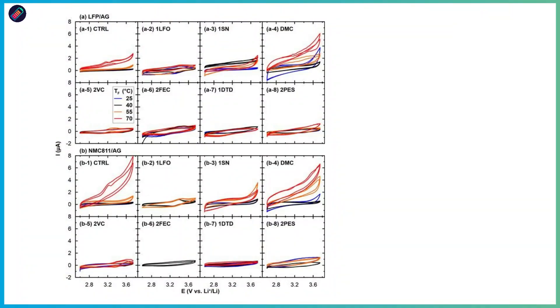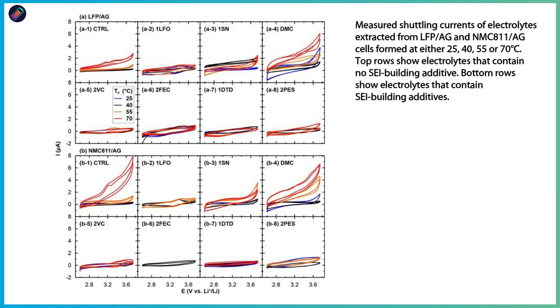Now we wanted to know — we had identified that our reversible self-discharge is due to a redox shuttle molecule — so we were interested in how it is created in the first place, and what redox shuttle molecule it actually is. I did cells with many different electrolytes and performed formation at different temperatures. What we noticed is that especially if you use additives that have no SEI-building properties, or no additives at all, and you do formation at higher temperatures like 55 or 70 degrees Celsius, you get a high self-discharge. So we suspected these electrolytes contain redox shuttle molecules.